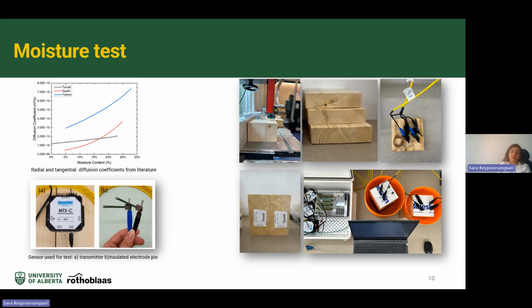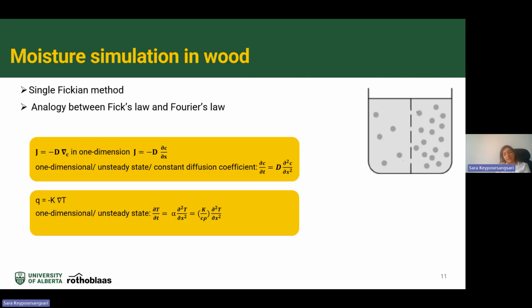In order to simulate the moisture transport inside the wood, we need to have the diffusion coefficient. So we did a parametric study, and based on that, we found the best diffusion coefficients for our samples. In this simulation, we used the single Fickian method, which is a practical method for finding the moisture transport inside the wood, which is based on Fick's law.